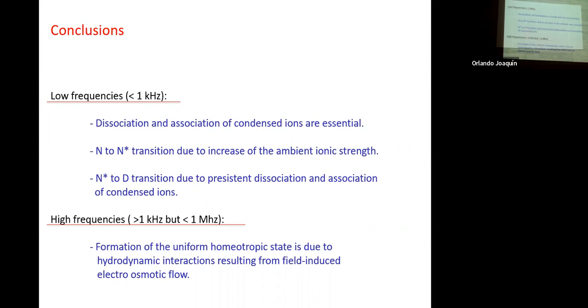At low frequency, it's essential that you can polarize things—that's necessary to peel off the condensed ion. But at high frequencies, you cannot do that anymore. The hypothesis is that the formation of this uniform homeotropic state is due to hydrodynamic interactions related to electro-osmotic flow.